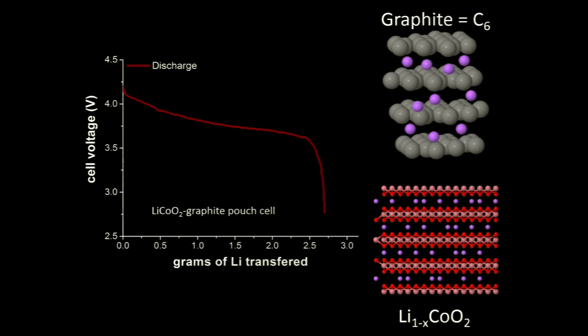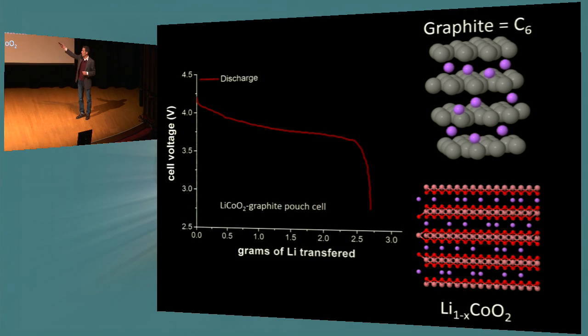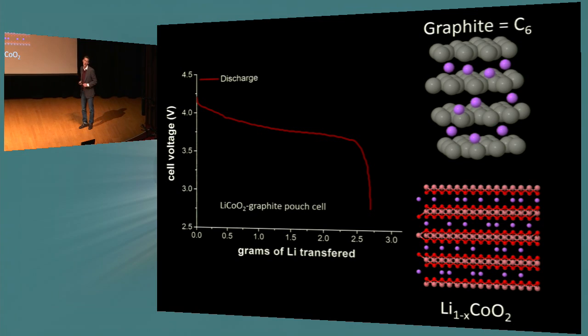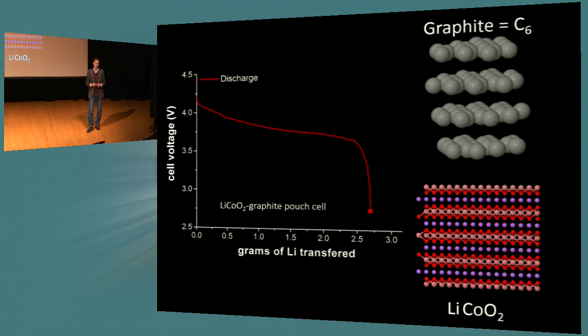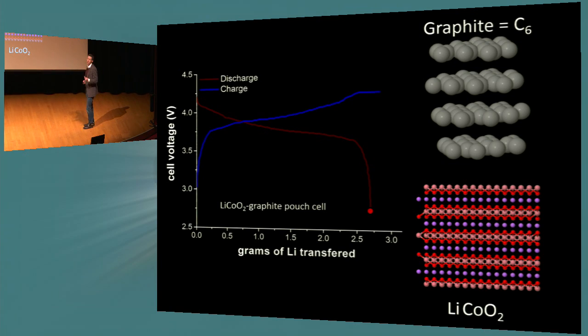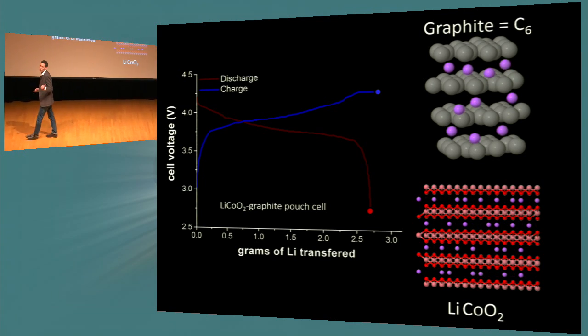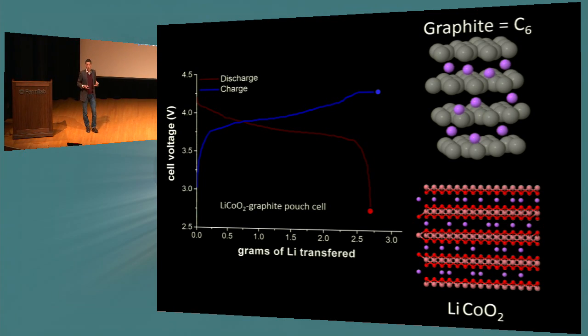How does a lithium ion battery work? So there's two materials on either side of the battery. There's a graphite, which has lithium in the layers. Lithium is these purple spheres. And over on the other side of the battery, you have a cobalt oxide phase, layered phase, that has a little bit of lithium. And what I'm showing here is the voltage of the cell as lithium literally moves from one side to the other. So all the lithium went from the graphite over to the cobalt oxide. Now, right now the battery has no energy left in it. We've discharged it. We've used it. We've run our cell phones. We have to put energy back into it. So we plug it into the wall and the exact opposite happens. That lithium moves back over to the graphite and you have a voltage on your cell and you have stored energy again. And that's how lithium ion battery works.